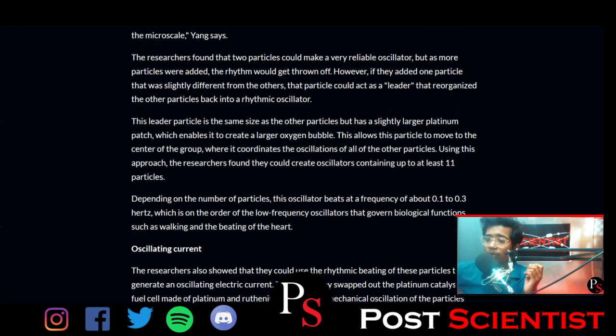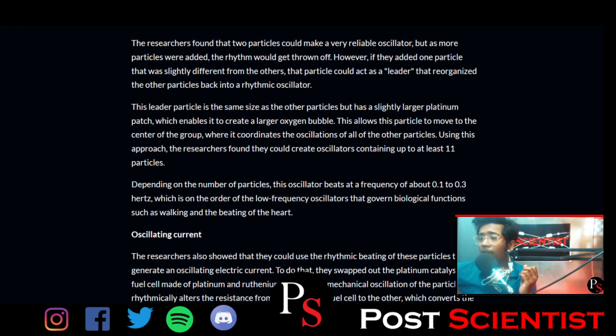Yang says the researchers found that two particles could make a very reliable oscillator, but as more particles were added, the rhythm would get thrown off. However, if they added one particle that was slightly different from the others, that particle could act as a leader that reorganized the other particles back into the rhythmic oscillator. This leader particle is the same size as the other particles, but has a slightly larger platinum patch, which enables it to create a larger oxygen bubble. This allows the particle to move to the center of the group, where it coordinates the oscillation of all of the other particles.